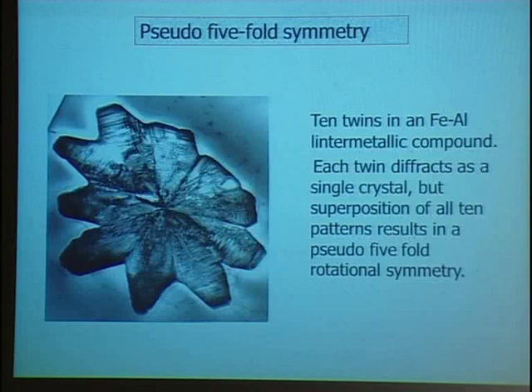Now, if you take a diffraction pattern from one of these crystals, then of course you will receive a periodic diffraction pattern. Nothing new. However, because you have 10 different crystals here, and the angle between them is 36 degrees, 360 divided by 10, if you take a diffraction pattern from all of them together, then you will have 10 diffraction patterns superimposed, and each one is 36 degrees to the other. So you'll have 1, 2, 3, 4, 5, 10 of them. And of course, you'll have a 10-fold rotation symmetry, which is shown here.